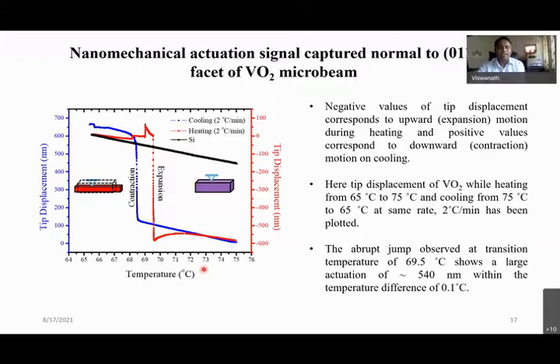I need to add a disclaimer here. We have not calibrated any noise or any other thermal effects. I'm at least aware of Professor Preeta Pant at IIT Bombay, who has a good piece of work in calibrating the thermal effects. In this case, we have not done that, but we have taken a standard sample. If I take a single crystalline silicon and do the same experiment in the same interval, everything else constant, same load applied, same temperature interval, I know this is the displacement or the distortion introduced by the thermal effect. It is going from 600 to maybe around 550 nanometers, right?